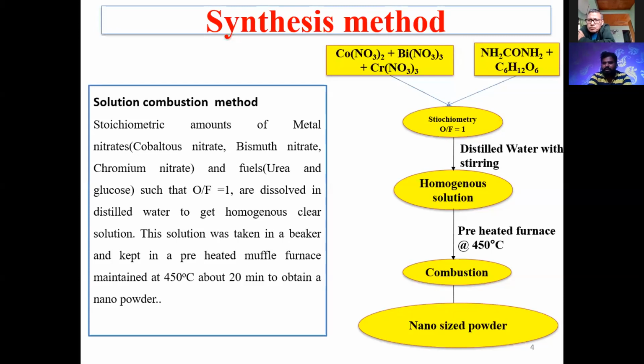This homogeneous solution was kept in a preheated muffle furnace at 450 degrees Celsius for the combustion process. This process takes within 20 minutes. After 20 minutes, we get a nano size powder. This powder can be washed using water.